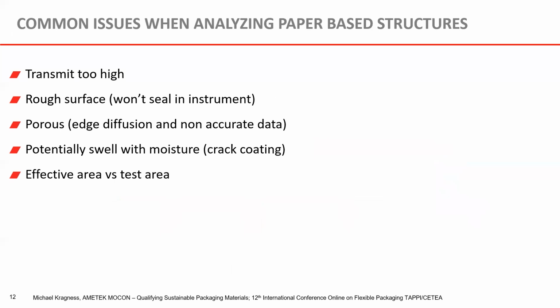You could have it transmit just too high. You know, paper is not a good barrier, and if you put a coating on it, maybe the coating has a pinhole or the coating is not consistent. Maybe it has a rough surface. A lot of coated paper has a very rough surface, and rough surfaces do not seal too well in instruments because you need a smooth interface, because we're dealing with gases. So if we have a gas on each side, we need to be sure that we're creating a hermetic seal between the two sides. You can have porosity issues, which is what I just spoke of in the slide before.